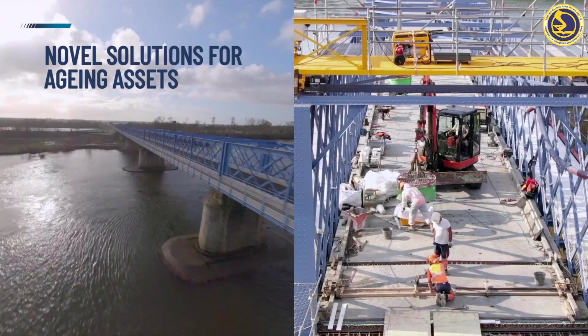You see recoating of the steelwork, localized repair of corrosion on the steelwork, which is obviously something that you typically try to do when you do such an intervention. But then here, particular was, unfortunately, you don't see it here on the photo, was the bridge deck, which you have transverse steel beams. And then between the steel beams, you have these masonry shallow arches or voûtes spanning between individual steel beams, and then a very low quality concrete road deck on top.